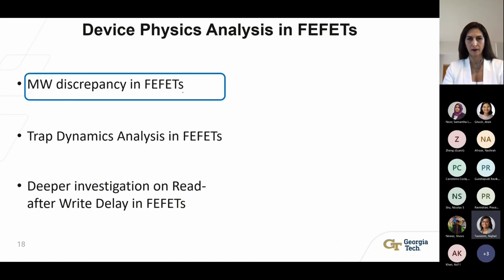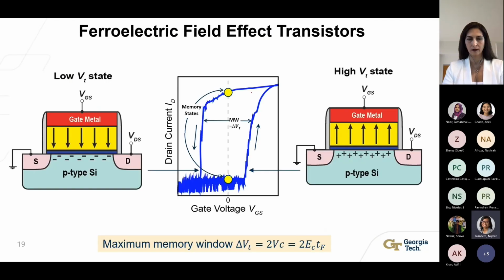The first one is the memory window discrepancy in FeFET. Now, what do I mean by memory window discrepancy? As I've mentioned before, the memory window in an FeFET is nothing but the shift in threshold voltage when the polarization is switched. And the maximum memory window that we get out of FeFETs can be theoretically represented by this equation over here, which shows that it is equal to 2 times its critical electric field multiplied by the ferroelectric thickness. But in reality, this is not something we see.